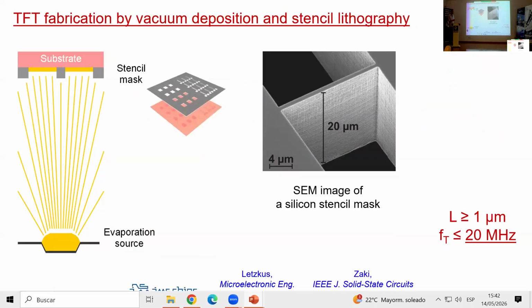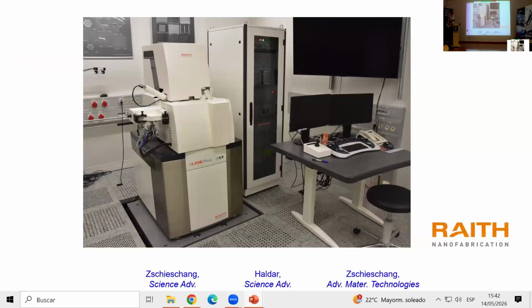And another technology is stencil lithography that we have put a lot of effort into the last 10 years or so. In stencil lithography, we use these silicon stencil masks. These are 20 micron thick silicon membranes into which we open holes in specific locations by a combination of electron beam lithography and deep reactive ion etching. And then we use these masks to deposit the functional materials, the gate electrodes, the source and drain contact, organic semiconductor, through the openings in these masks. We build up the transistor layer by layer. And with these masks, we have a resolution on the order of 1 micron. And that can get us into the range of transit frequencies on the order of about 10 to 20 megahertz.